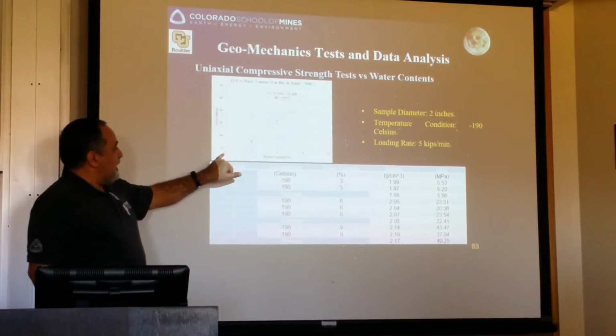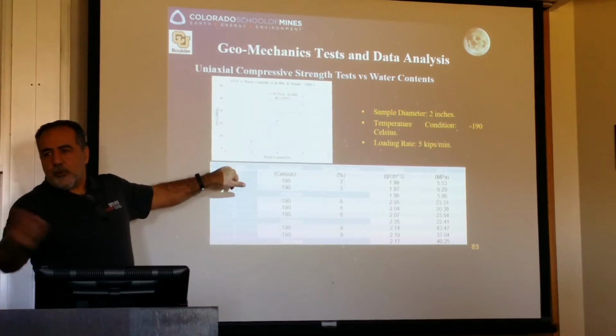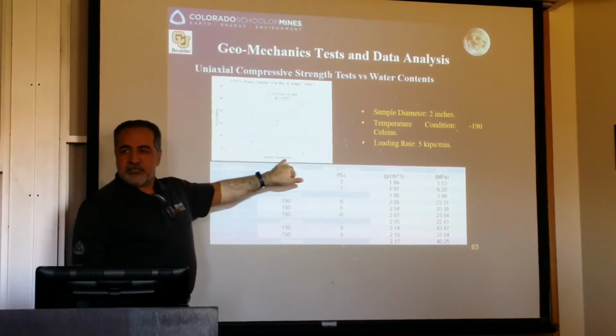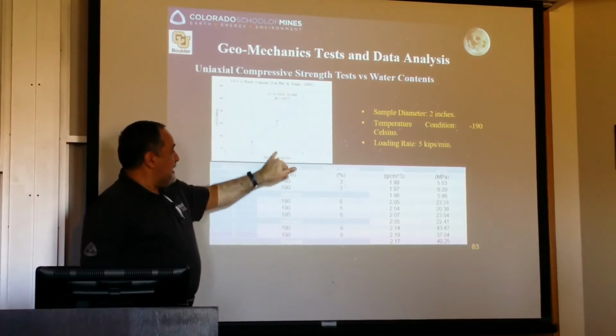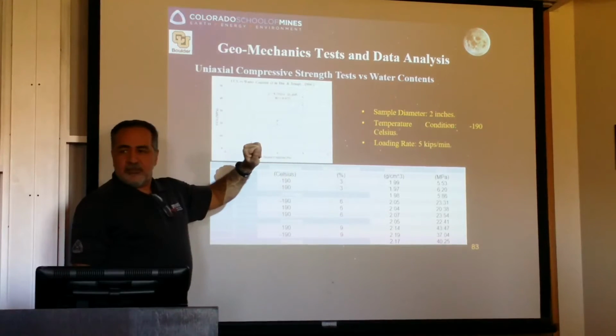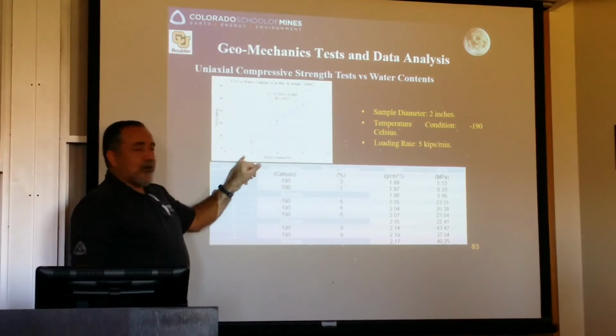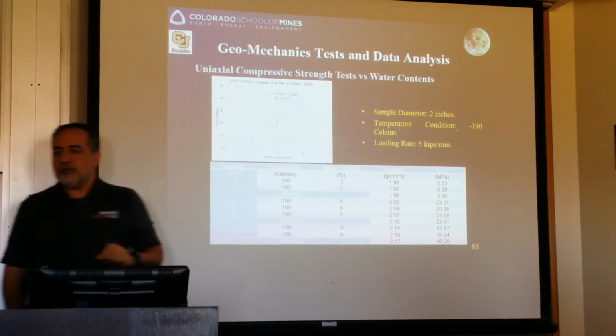But the beauty of it is here. This is variable water content. From 0, we didn't go to 0, because 0 is just powder. It doesn't even hold up, right? 369. Remember 369? This is the median estimated water in the permanently shadowed crater, plus or minus 3. So we actually covered that bit. And see how beautifully it goes up. So it gives us a very good direct linear correlation between water content and strength.